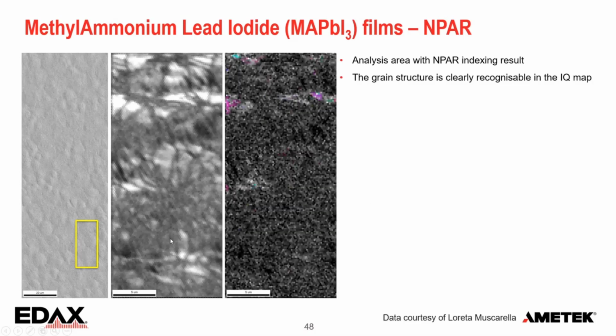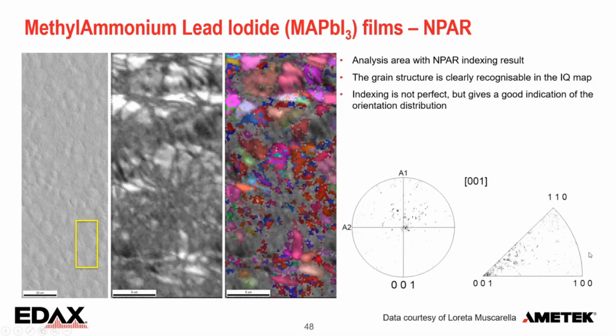So that's the original one. This is what NPAR can make of it. And when we index that, this is what we get. In most grains, we get a few pixels indexing. It's not 100%, but it's good enough to get a nice texture calculation and also a good indication of the microstructure.